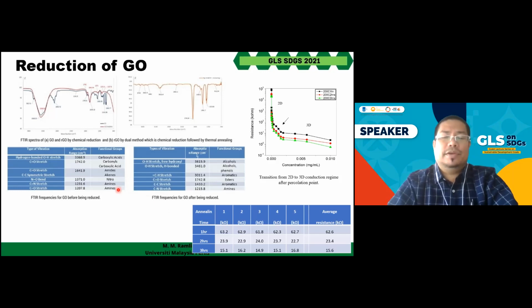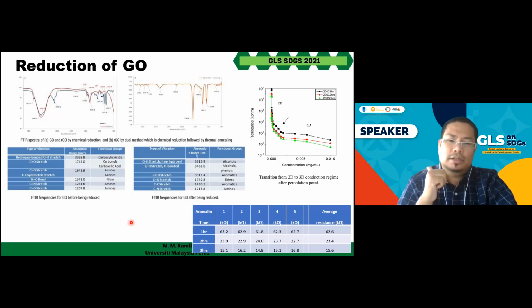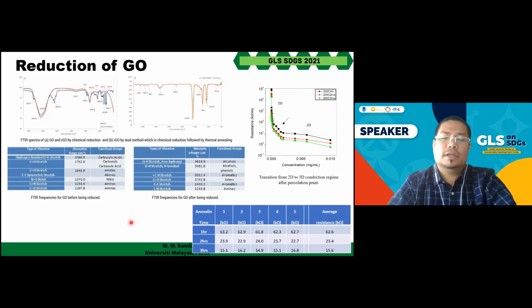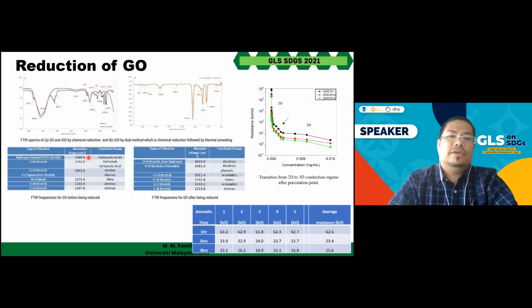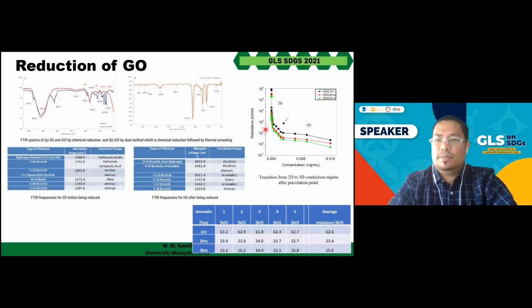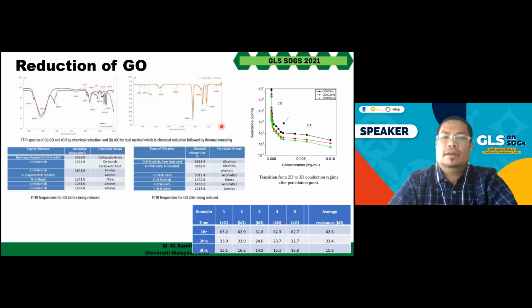So we did reduction. First, we do the chemical reduction. We are using sodium borohydride. And then for the second reduction method, we use thermal annealing. Okay. So for some of the applications, we just use sodium borohydride, and for some of the applications, we call it a double reduction: the sodium borohydride reduction and the thermal reduction. So if you look at the functional groups there, this is before the reduction and this is after reduction.